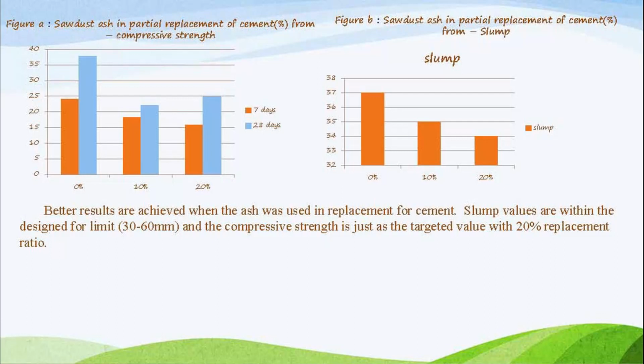If we look at the result, we find the compressive strength decreases for sawdust at about 10%, then increases when using a percentage of sawdust of 20%. The workability, or the slump test of the sample using sawdust, decreases about 20%. Then if we increase the percentage of sawdust used as replacement of cement, the workability also decreases.